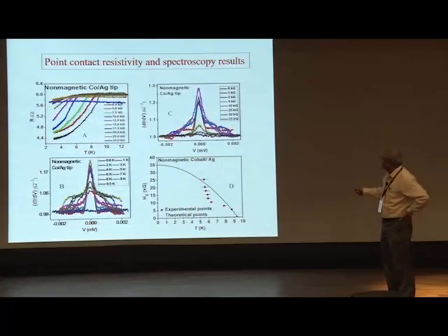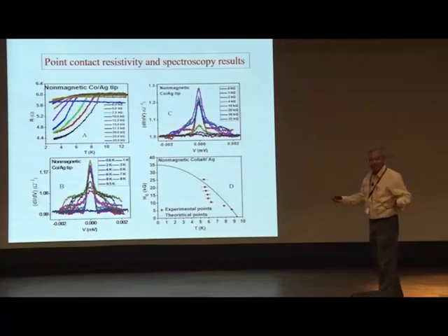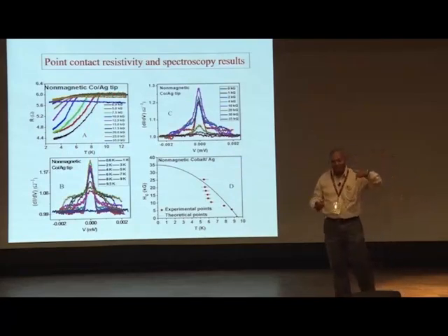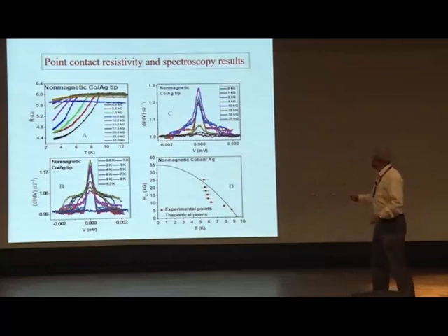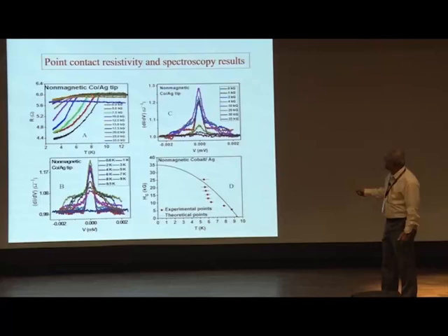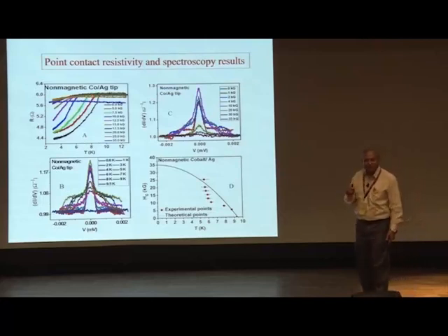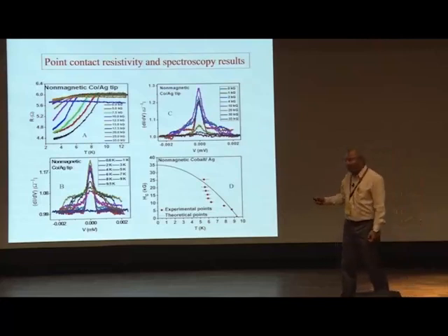You notice that at zero field, around 9.2 Kelvin, you have this drop in resistance. But it doesn't go to zero as a normal superconductor would, because you have the contact resistance sitting there. It's not just the pure superconducting material. If you apply magnetic field, the superconducting transition temperature shifts towards lower temperature. It's a definite sign of superconductivity in resistance.